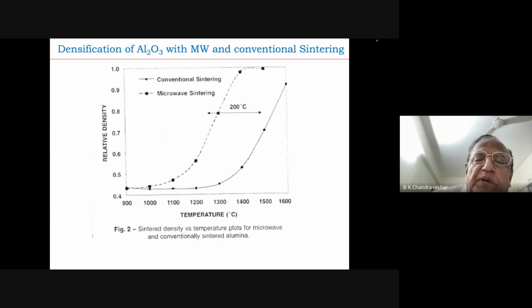They tend to join together and become bigger and bigger. What was 0.6 becomes 1, and 1 becomes 1.4, 1.5, like that. But it has to be done very slowly, because the furnace cannot go to normal quickly. In a conventional furnace, you cannot go to a very high temperature very quickly. It has to be done slowly, because if you heat it very fast, even the insulation bricks will crack because of what is called thermal shock.